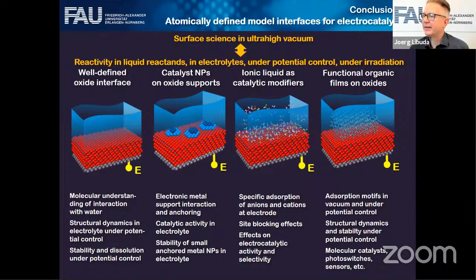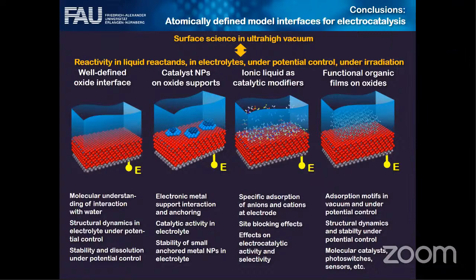Right. Yeah. So we systematically varied the concentration. It's in aqueous solution, by the way. So we systematically varied the concentration of the IL in aqueous solution and looked at the reactivity and the selectivity. And what you see is that you get this selectivity effect already at quite low concentrations of the ionic liquid. So it has a strong effect. And if you then further increase the concentration, the activity is very strongly suppressed. So if you go to higher concentration, the surface becomes inactive quite fast. So it's very sensitive. Cool. Thank you.